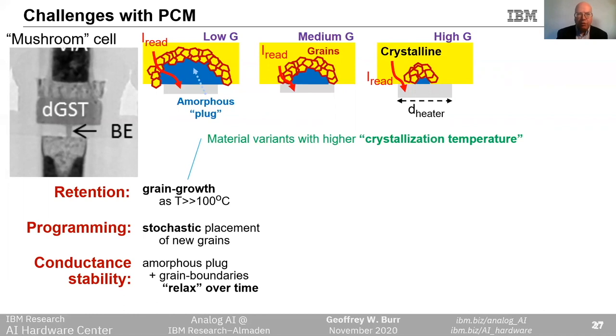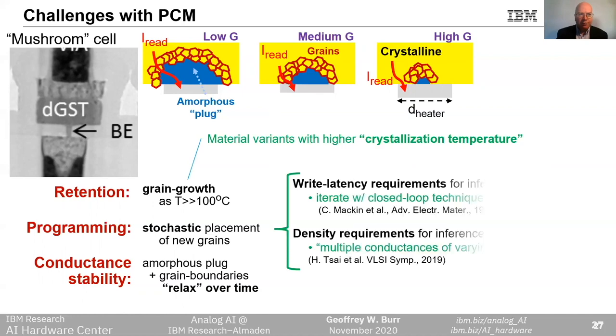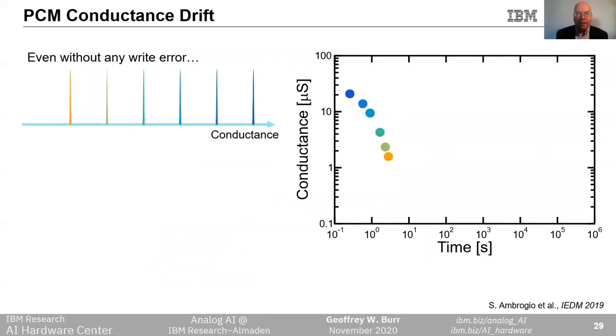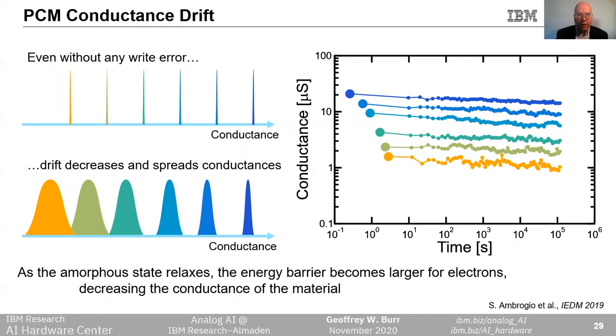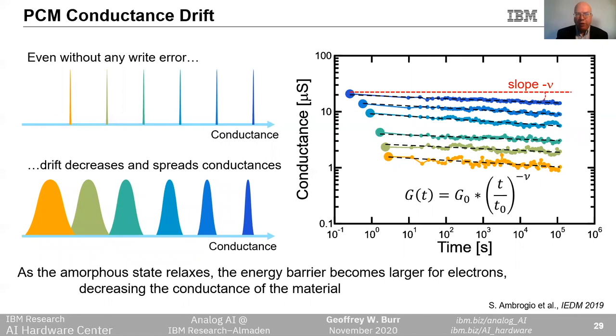The same physics that enables fast crystal growth is still slowly working away at lower temperatures, eventually leading to retention issues. We can tune this by using PCM materials with higher crystallization temperatures. In terms of programming, the physics of grain nucleation means each pulse generates some new configuration of grains, so there is some fundamental stochasticity. The latency requirements for inference are much more favorable than in a memory application, so we should have enough time to do iterative closed-loop tuning of the conductances. We can also trade off some areal density to get more redundancy and SNR using what we call multiple conductances of varying significance. However accurately we program the conductance state, we need to maintain that state over time. Unfortunately, continued relaxation of the amorphous phase contributes to conductance drift.